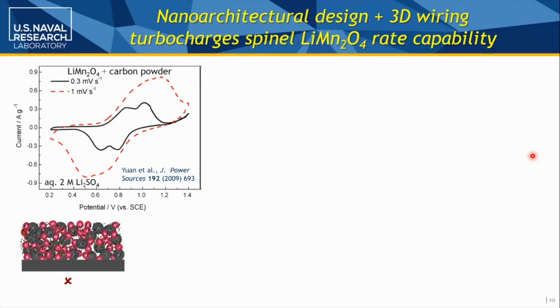And people have studied the lithium spinel as a battery material in aqueous lithium sulfate. So here's one paper that came out last decade, ground up with carbon powder. And you can see if they're going sort of battery slow, 0.3 millivolts per second, you can see some resolution of those Faradaic peaks. But once you're at a millivolt per second, you've lost that resolution. And this is a classic powder composite.